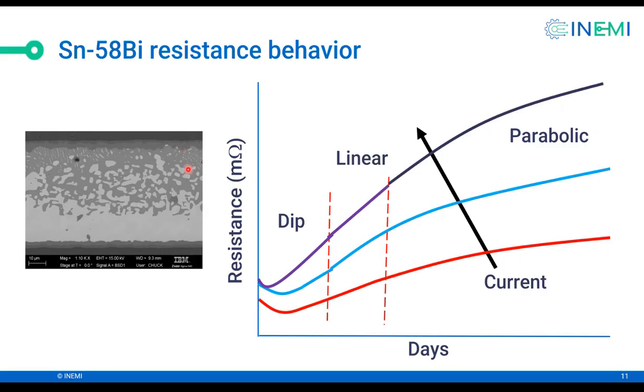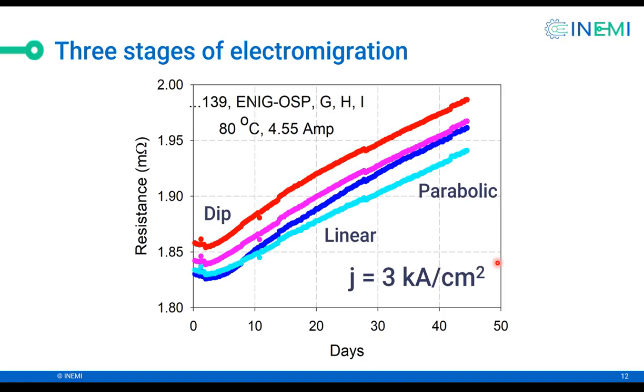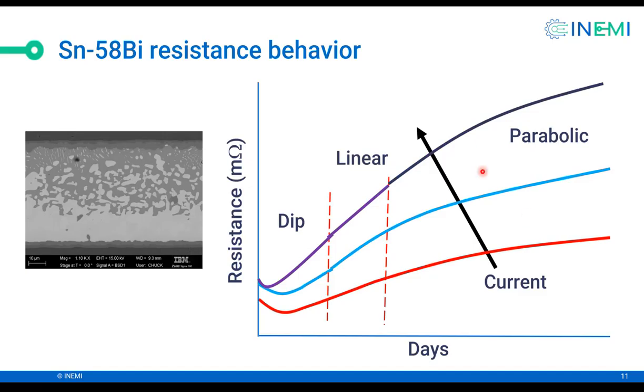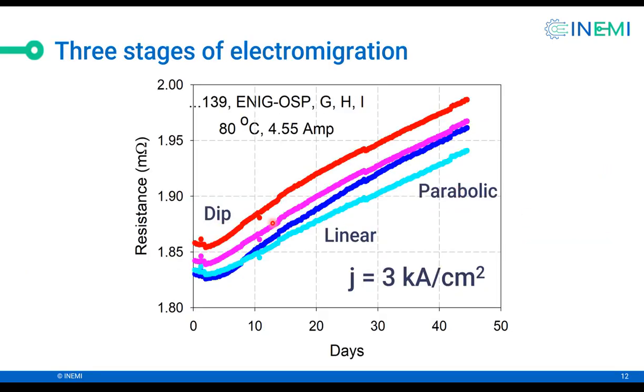Okay, so what we learned in our study is when you plot resistance versus time for a solder joint like shown here, initially there's a dip in resistance. Then the resistance rises. It becomes linear for some period, and then it becomes parabolic. Let me explain why we have these three regions. Before I do that, this was just a cartoon, but here is actual data for different solder joints. So we have the dip region, the linear region, and then the parabolic region.